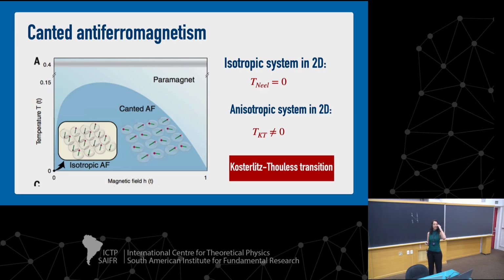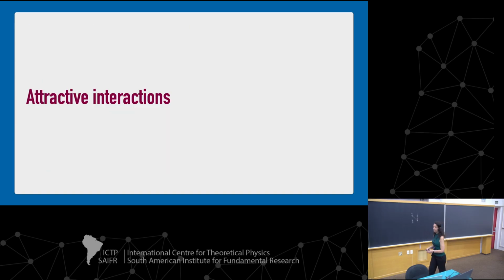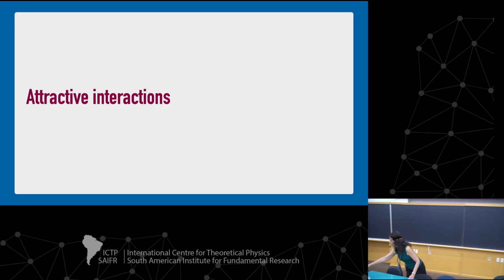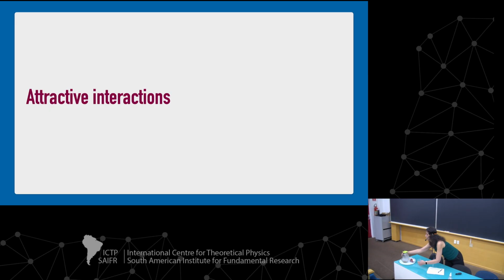I've mentioned before that when Markus Greiner was looking into correlations, he said he had a long-range order, but he cannot have that because he is in this limit here, and the critical temperature here is 0. But as long as you break the degeneracy between out of the plane and in plane, then you can have this Kosterlitz-Thouless transition, and the critical temperature rises and decreases with magnetic field. And this gray line here is the temperature where the experiments are. So I'll talk a little bit about this. And this is very similar to what happens in attractive interactions.